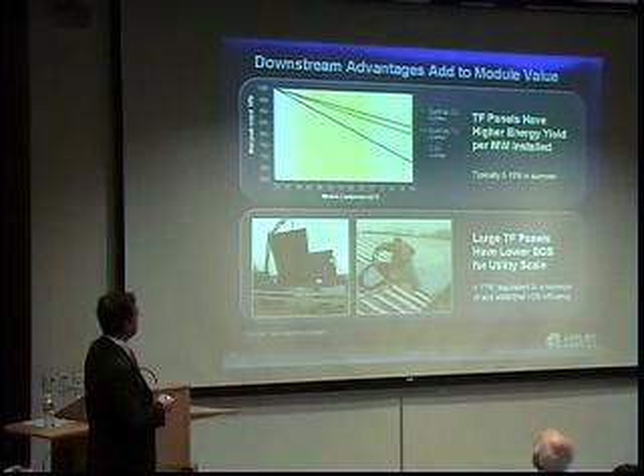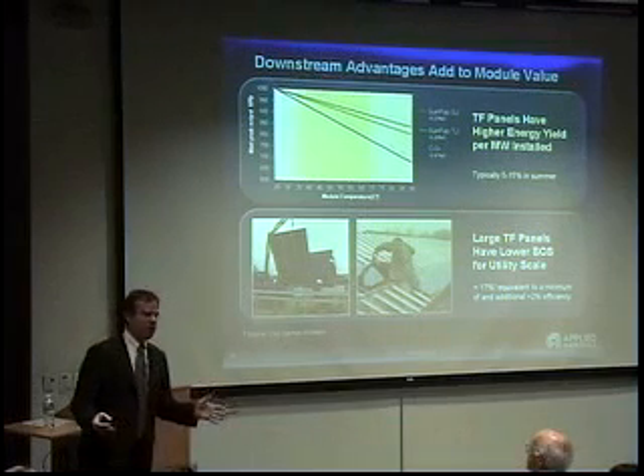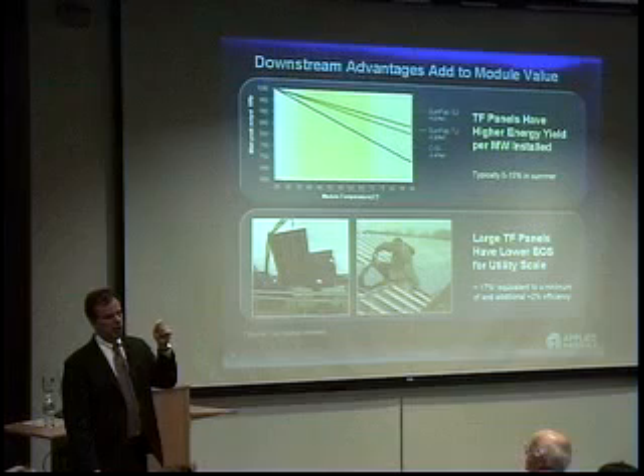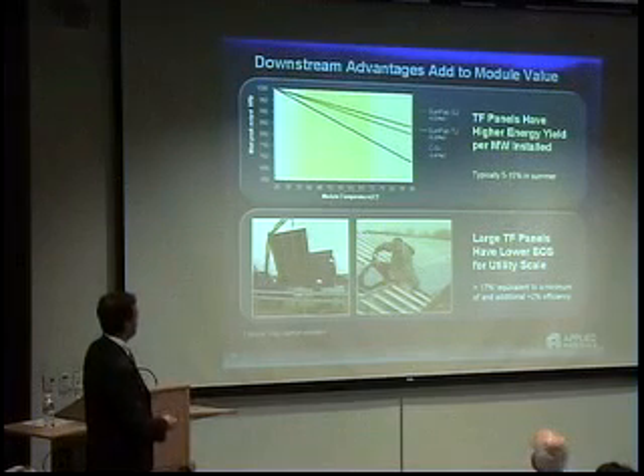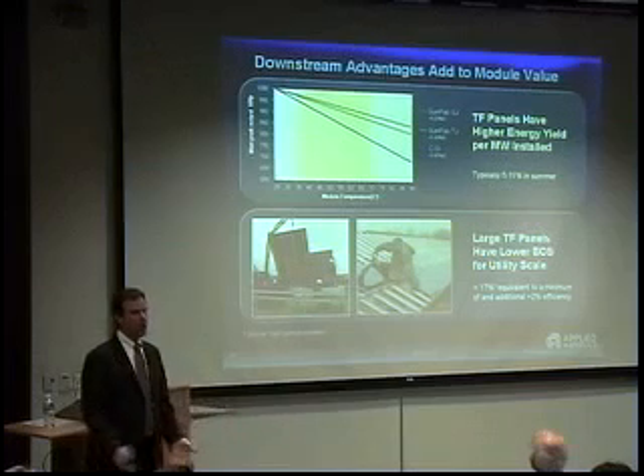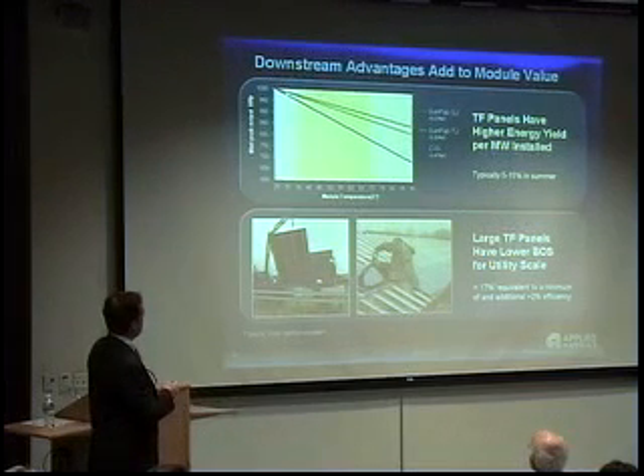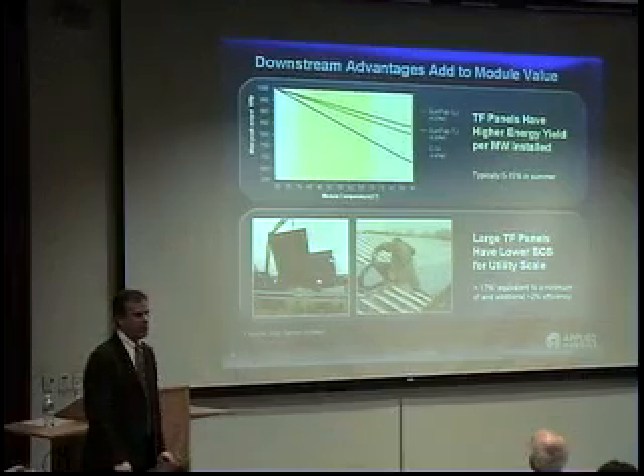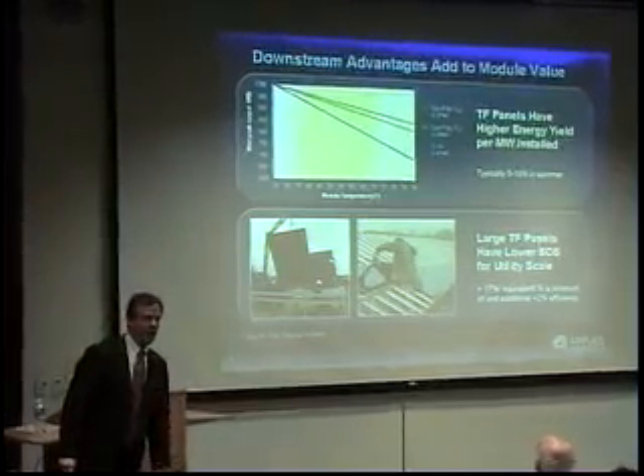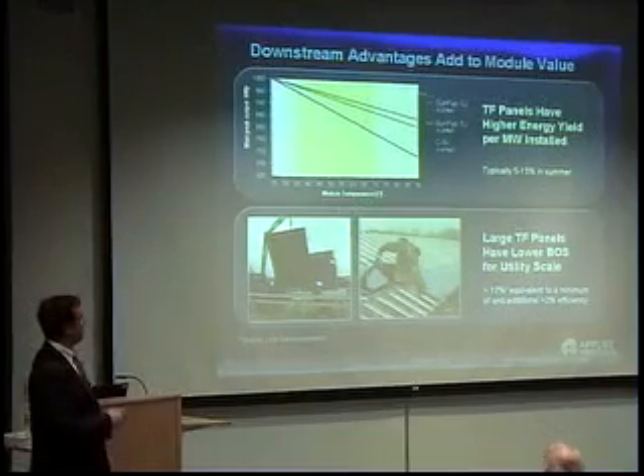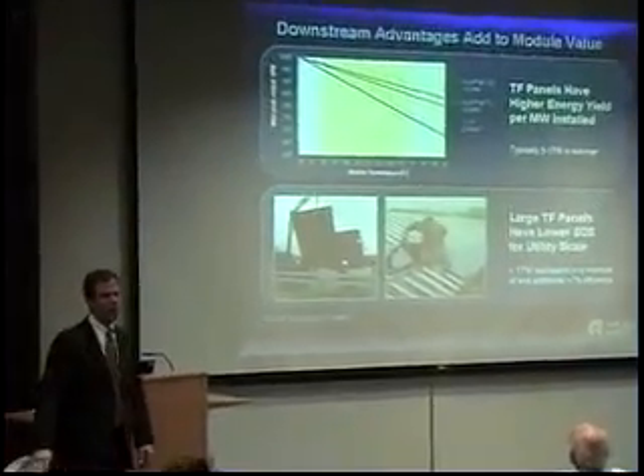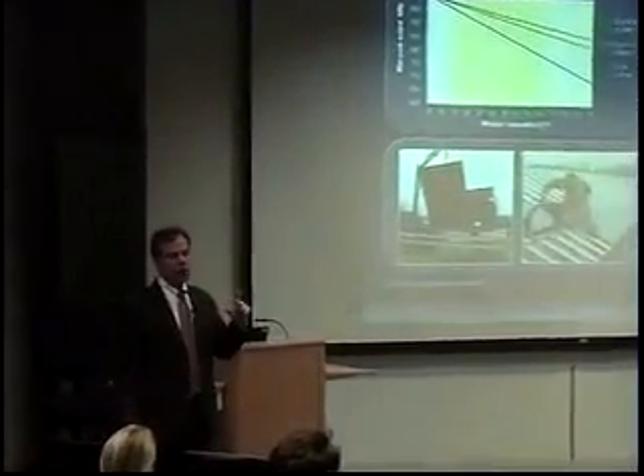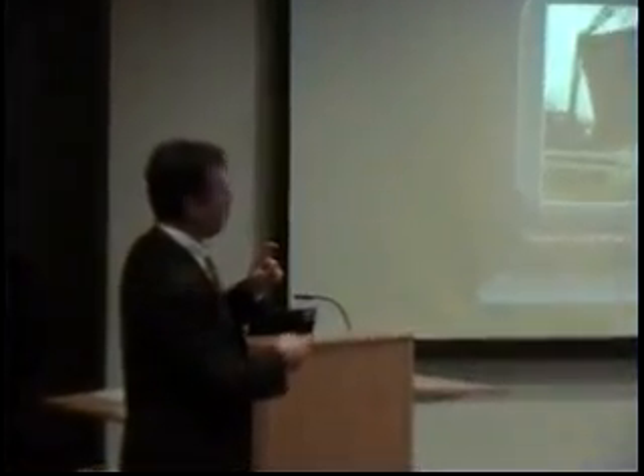One is the thermal coefficient. If you look at panels that are rated, or a set of panels for the same output in a cool climate under standard conditions, and you actually put them in the field in a desert or in any kind of environment where they heat up when they're actually working, you find that crystalline silicon degrades very fast with temperature. So if you put crystalline silicon in the desert, it's not very efficient. It loses a lot of efficiency. The thin film silicon loses a lot less, and so it behaves better. It gains in performance as it's heated up versus crystalline silicon in a relative way. So that means that thin film panels get higher energy yield in real conditions versus crystalline silicon for equal rated panels. So that's a benefit.